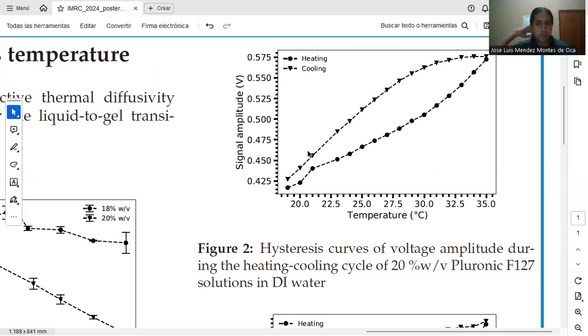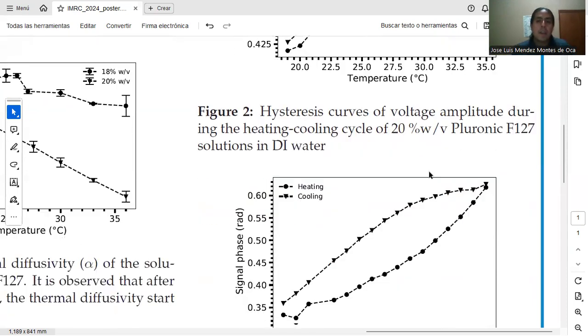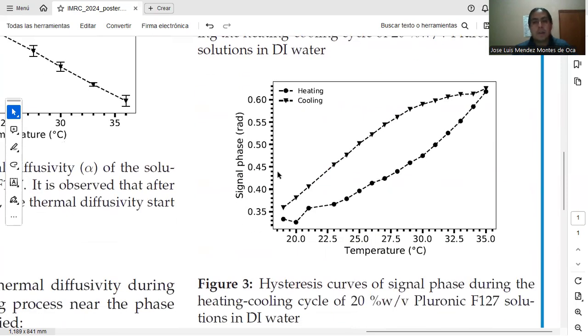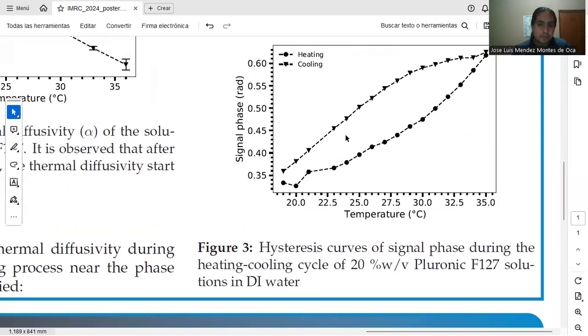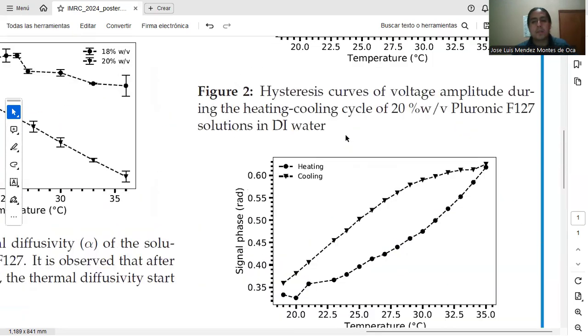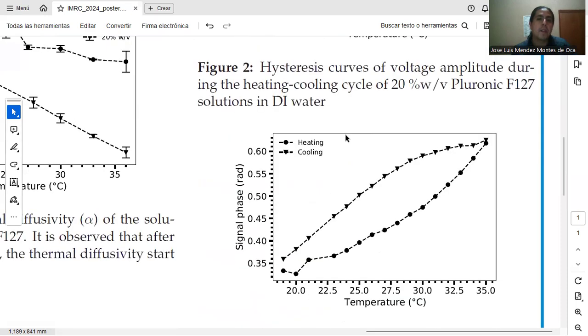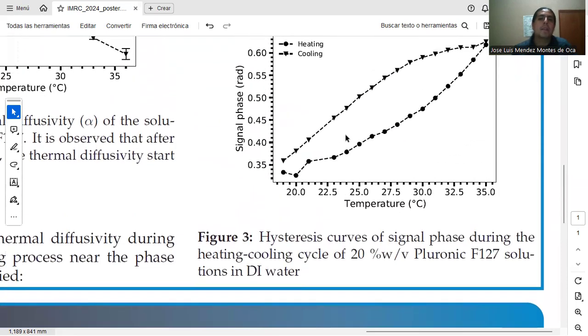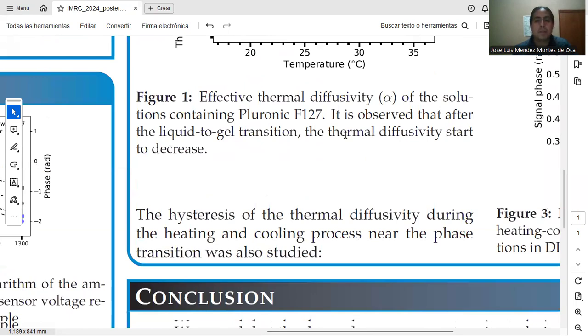It was not observed. And we regard that this is because once the polymeric chains are entangled, it is difficult to untangle them even when the temperature is decreased. And we obtained a similar behavior observing the signal phase, very similar to that observed with amplitude. And these are our prior results.